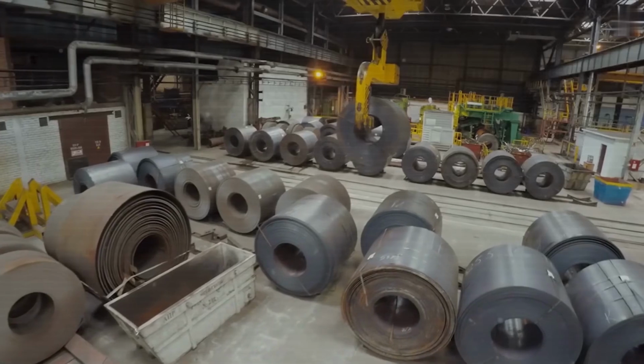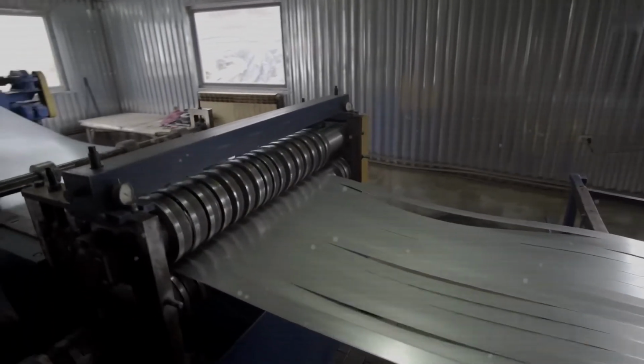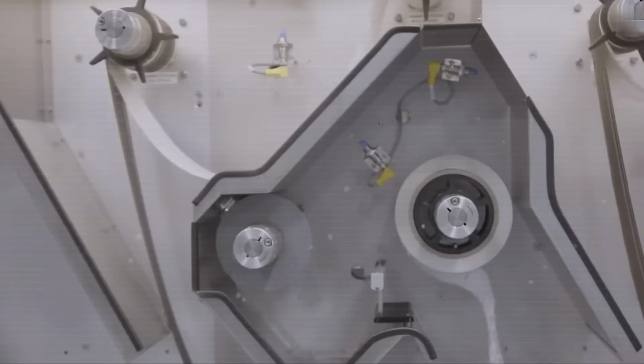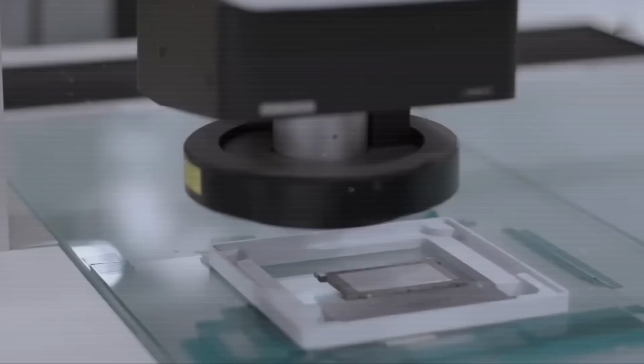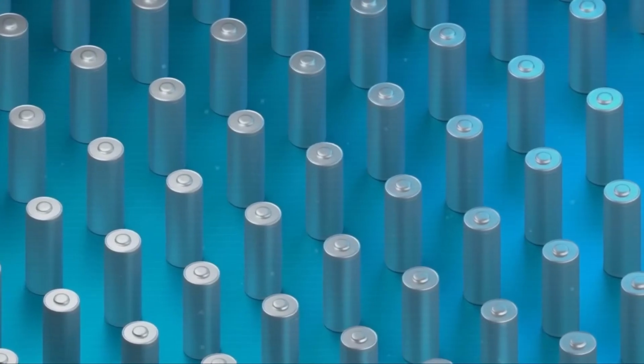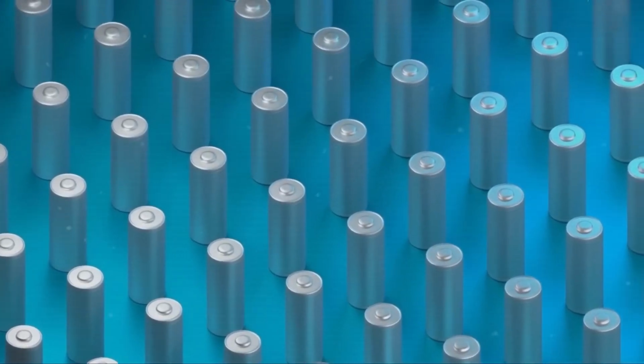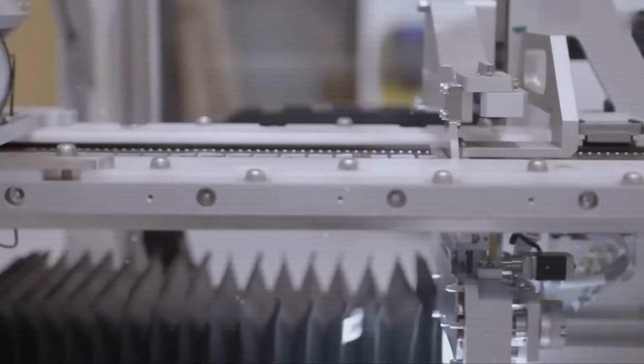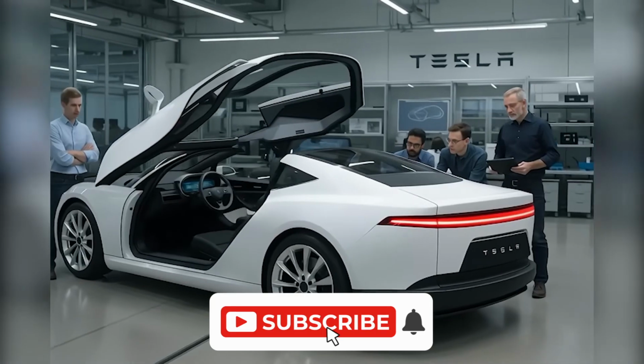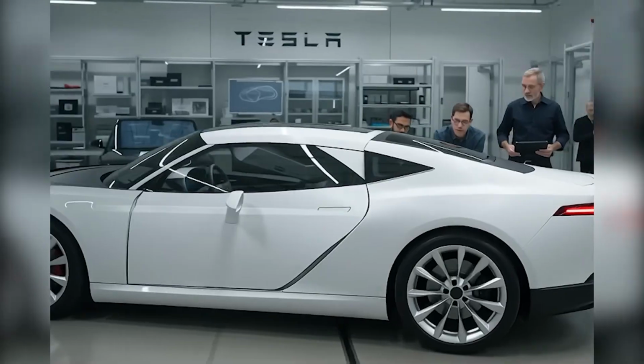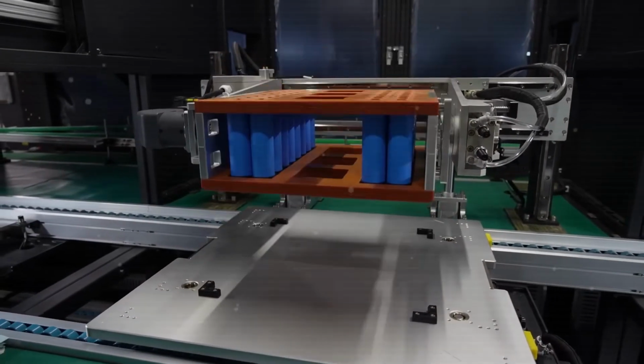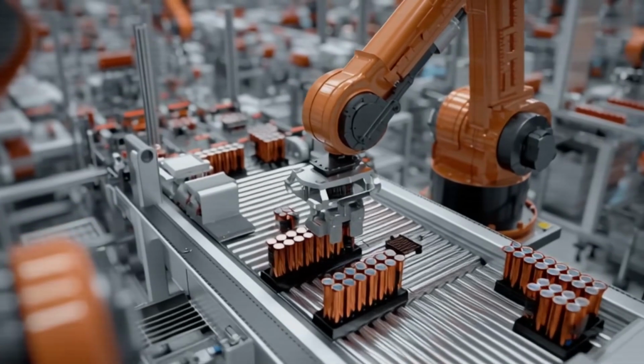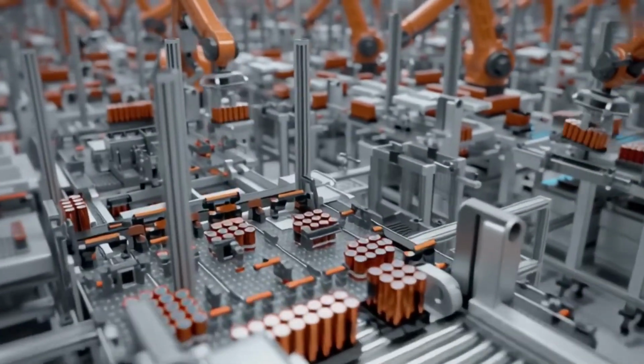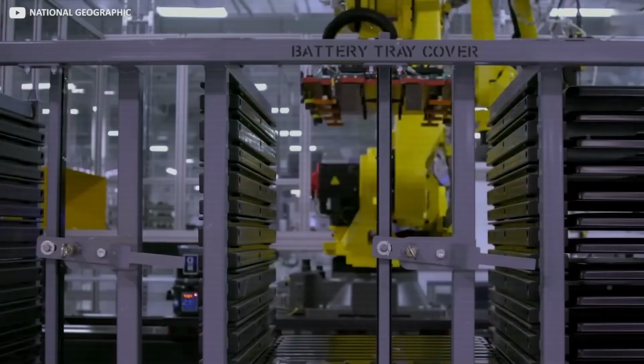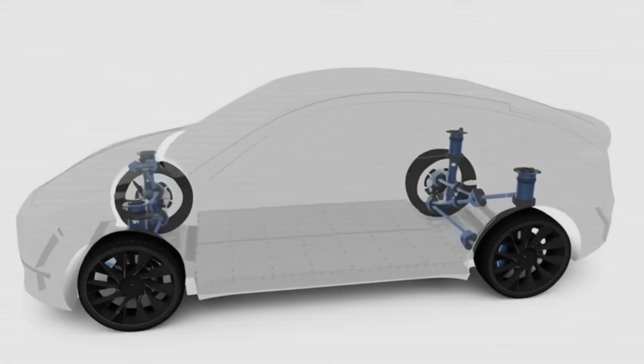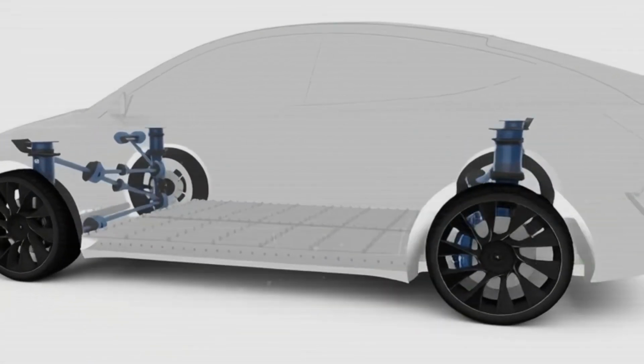Aluminum is one of the most abundant metals on Earth and costs roughly 15 to 20 times less than lithium per ton. That single fact ripples through the entire supply chain and reshapes battery economics. Current estimates place aluminum-ion packs at around $60 to $70 per kilowatt-hour, less than half the cost of today's lithium-ion equivalents. For a compact EV like the Model 2 with a 50 kilowatt-hour pack, lithium cells would cost about $6,500 before assembly. Swap them for aluminum-ion, and that number drops to roughly $3,200 to $3,500. That's more than $3,000 saved per vehicle, almost entirely from the battery alone.